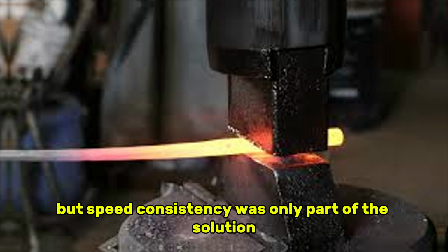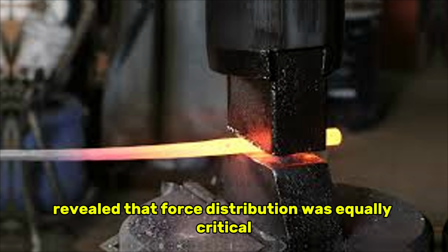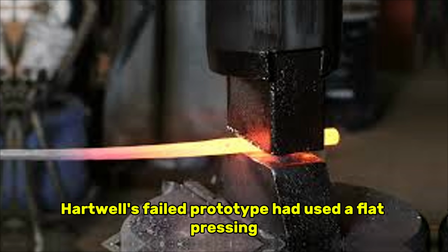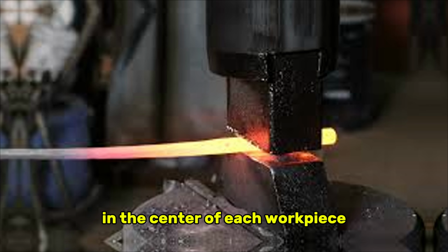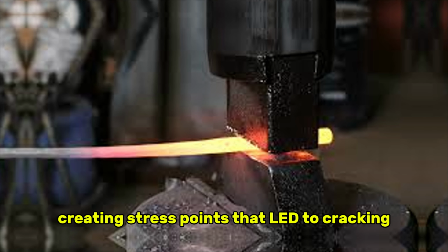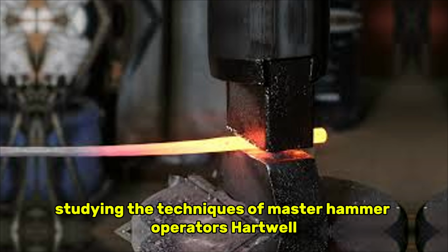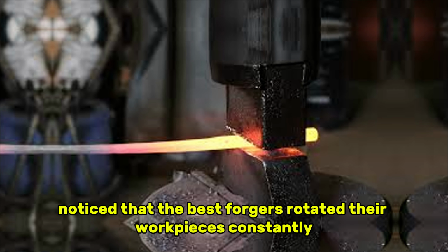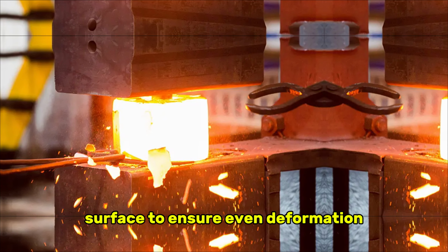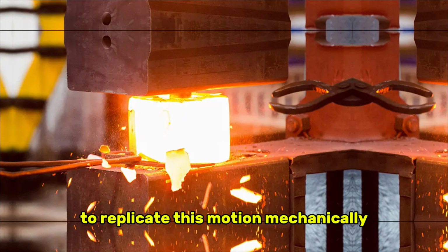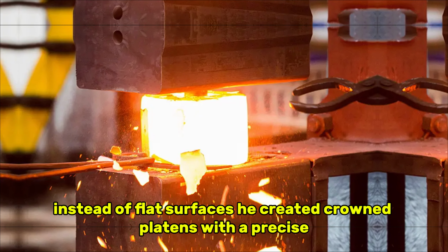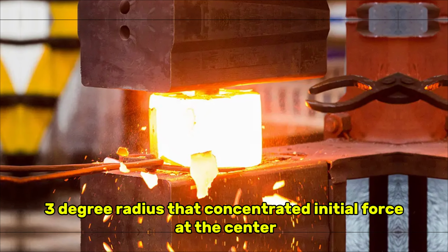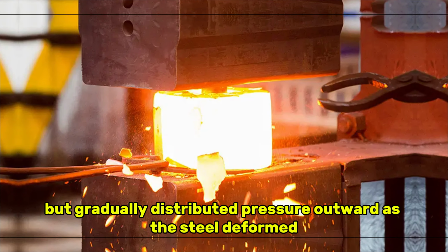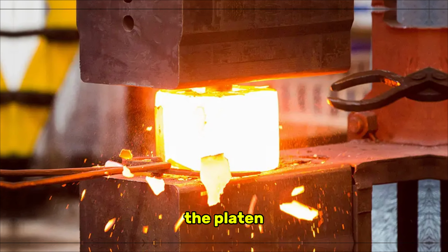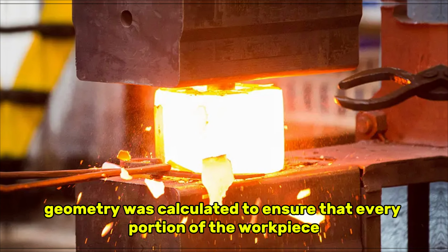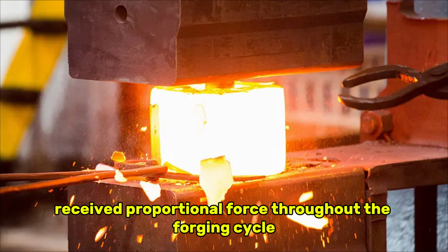But speed consistency was only part of the solution. Hartwell's analysis revealed that force distribution was equally critical. Hartwell's failed prototype had used a flat pressing surface that concentrated force in the center of each workpiece, creating stress points that led to cracking. Studying the techniques of master hammer operators, Hartwell noticed that the best forgers rotated their workpieces constantly, distributing hammer blows across the entire surface to ensure even deformation. Hartwell redesigned his press platens to replicate this motion mechanically. Instead of flat surfaces, he created crowned platens with a precise 3-degree radius that concentrated initial force at the center, but gradually distributed pressure outward as the steel deformed. The platen geometry was calculated to ensure that every portion of the workpiece received proportional force throughout the forging cycle.